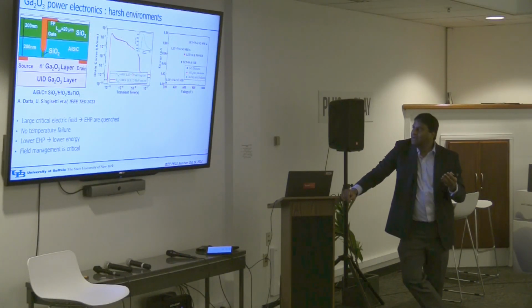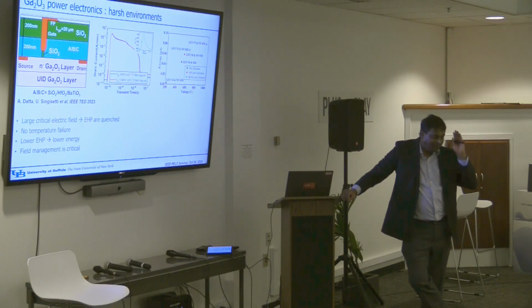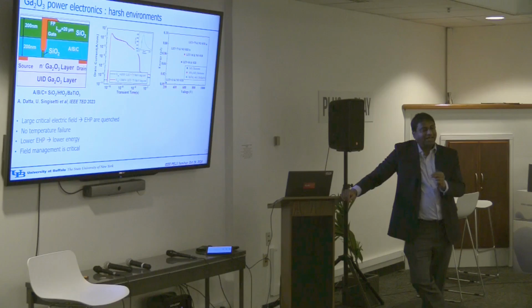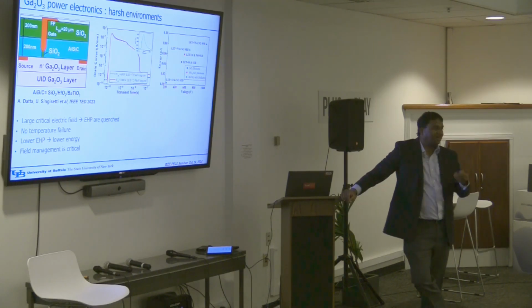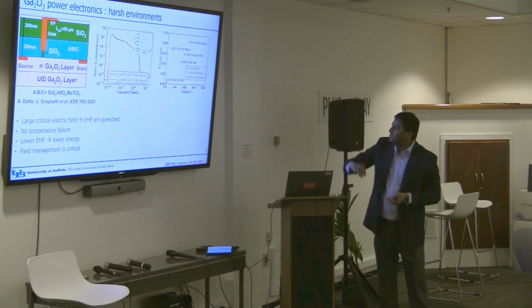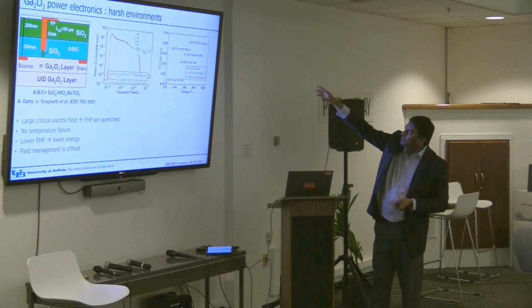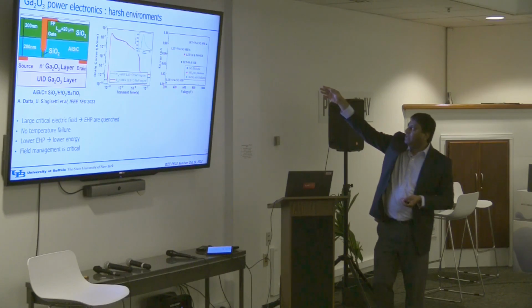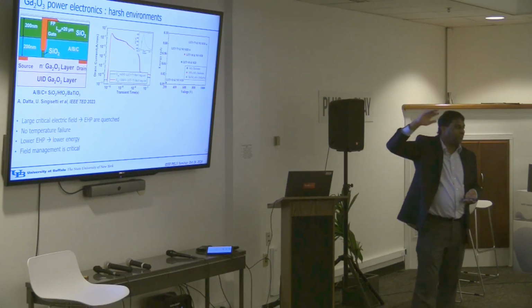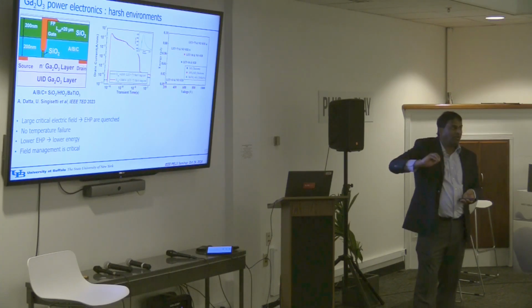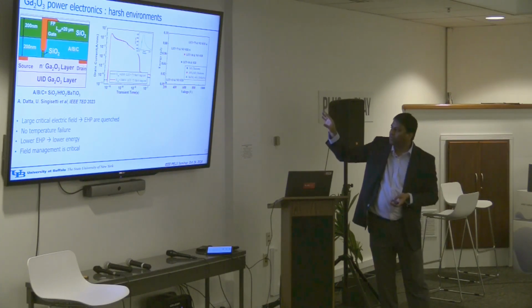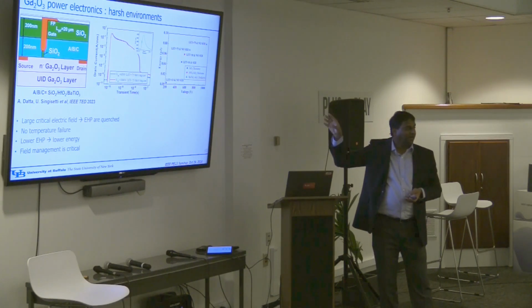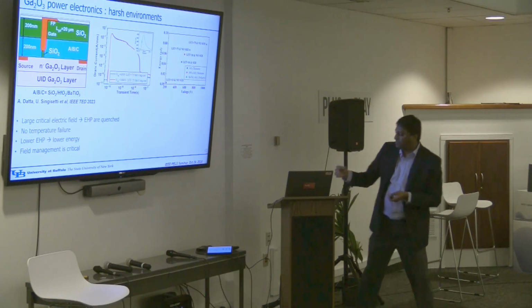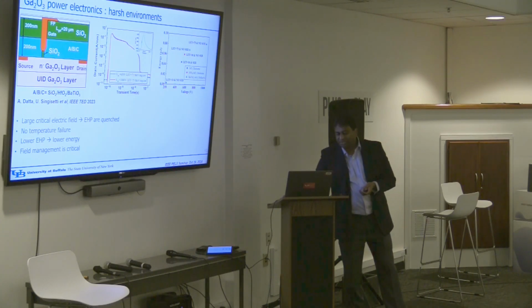But if you think about it, what is happening is that for the same energy of ion striking, you're creating less electron hole pairs, right? You're creating less energy compared to say silicon or silicon carbide. As a result, it's not failing thermally. You're not heating up much, right? So if you see the energy here, it's 0.1 picojoule in the maximum case, which is actually very low compared to say silicon carbide, which is in the nanojoule case, right? So you're creating very low number of electron hole pairs. As a result, you're able to tolerate thermally, right? So this is another example of gallium oxide where it could make an impact.